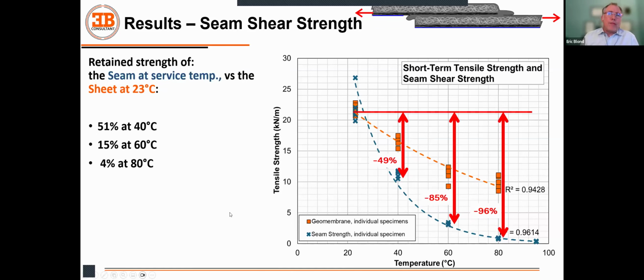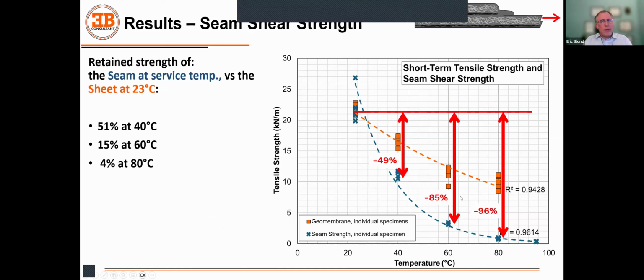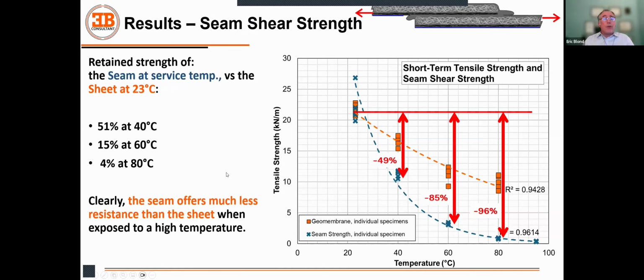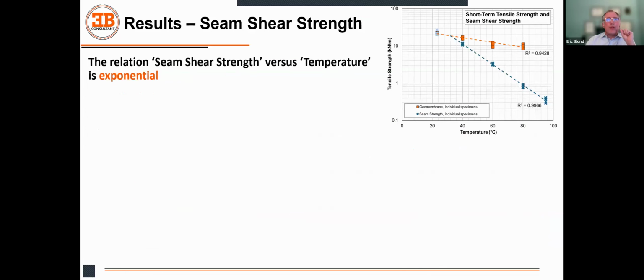And if we compare it to the initial value, at 40 Celsius, we have lost about half of the design strength of the product, that is the one that we usually consider for the mechanical analysis, and it goes up to 96% at 80 Celsius. So 80 Celsius is pretty on the high end. I'm not sure how often you would see 80 Celsius on a job site, on a black liner, but 60 Celsius is pretty reasonable as an assumption. Exposed to the sun, that's the range of values that we could expect to see. So clearly, the seam offers much less resistance than the sheet when exposed to a high temperature.